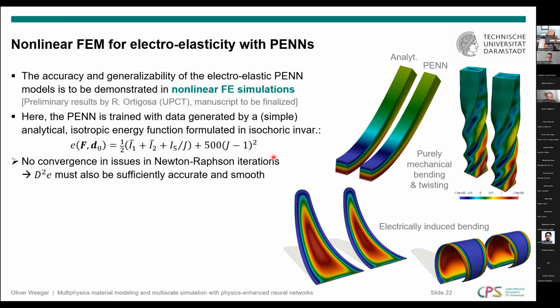Now, if we look at a combination of electric and mechanical behavior, here basically we have a gradient of the electric field throughout the height of this very thin membrane. And this gradient in the electric field introduces bending. And this is just a comparison of two different electric fields, here medium and here large, where you see again the comparison between analytical and neural network model, which are hardly distinguishable.